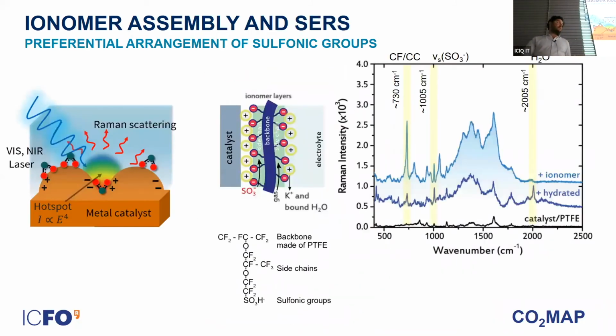We looked into Raman spectroscopy to try to understand how these ionomers assembled on the copper electrode. In surface-enhanced Raman spectroscopy, you can get really high resolution of the molecular fingerprints of these ionomers. And we are lucky because the substrate is a metal already, so you have SERS by default. You can see here in this plot the Raman intensity versus wave number for the reference, the catalyst over PTFE, and you can see how everything changes once you add the ionomers. You have different peaks corresponding to the different vibrational modes of the different parts of the ionomer.